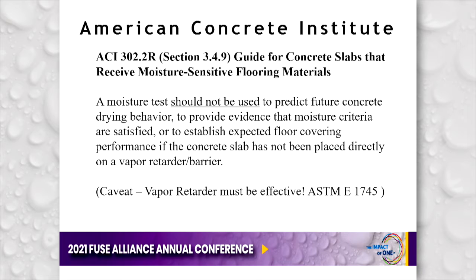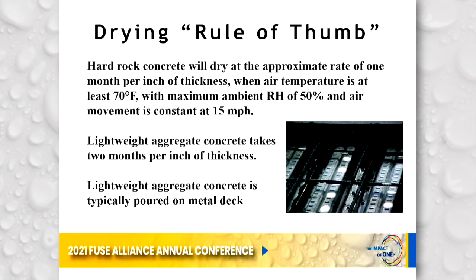So I think we also have to have a background knowledge of drying of concrete. And there are some rules of thumb that were published years ago by the Portland Cement Association. The first one is that hard rock concrete will dry at the approximate rate of 1 month per inch of thickness when air temperature is at least 70 degrees Fahrenheit, maximum relative humidity of 50%, and constant air movement. That doesn't happen very often. But if you've got 5 inches of concrete, it's probably going to need at least 5 months to dry under ideal conditions. If your GC calls you at 90 days and says, we need a floor installed, know that that concrete is not dry before you ever did any testing.